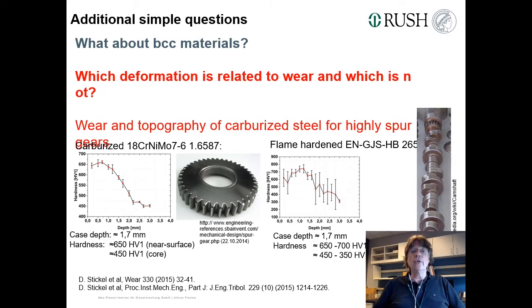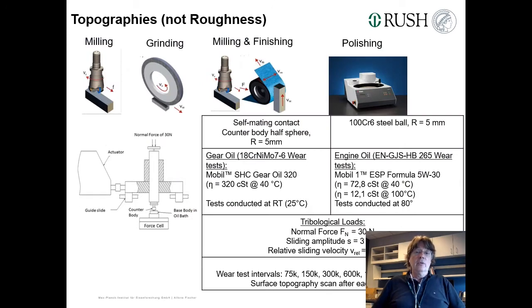So what do they do? We had different ways to generate the surface. It was a milled surface, a ground surface, a milled and finished surface. So you could still see the milling lines, but the peaks were a little bit flattened. And we also had a polished surface for comparison, because most tribo tests in the lab are done with polished surfaces and not with the real surfaces at the end of a classical fabrication process.